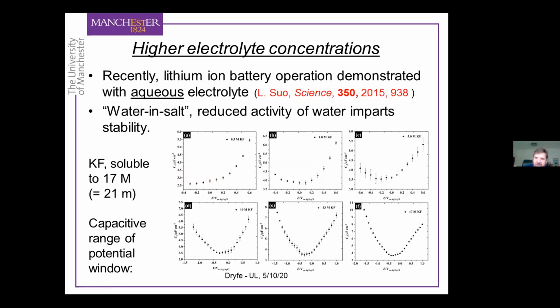Then you start to get into some kind of oxidation or reduction reaction. But at the high concentrations, once you go above 10 molar particularly, that potential range extends to about 3 volts, which essentially is entirely consistent with what these guys were reporting, that you can massively extend the potential window of water by having a very high concentration of salt. So it's quite an interesting experiment, and you see all sorts of strange phenomena, I think, working at these very high electrolyte concentrations.